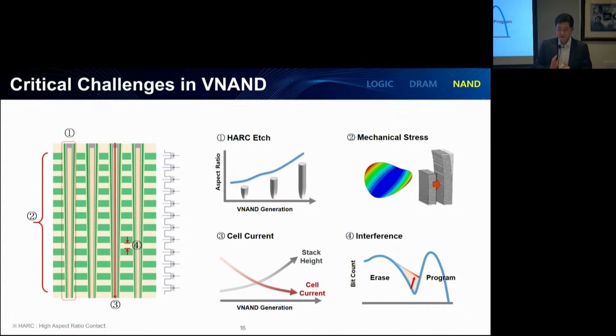So, what are the critical challenges to sustain NAND stacking beyond 1,000 layers? Currently, we are at around 250 layers. And there are 4 critical challenges. These mainly come from ever-increasing total stack height, including high aspect ratio etching, the HAR etch, and the mechanical stability, and low cell current, and interference between cells. As we stack more and more layers, ensuring the structural integrity is crucial to achieve our density goals.